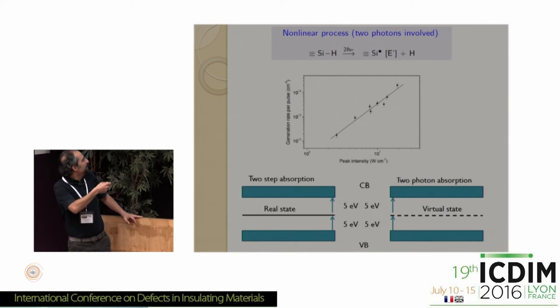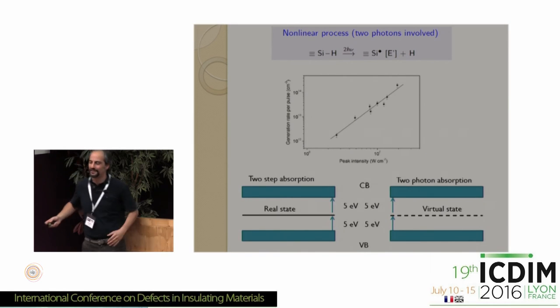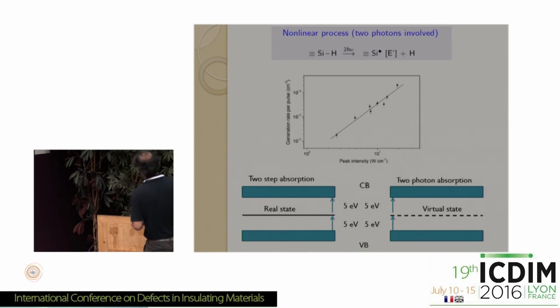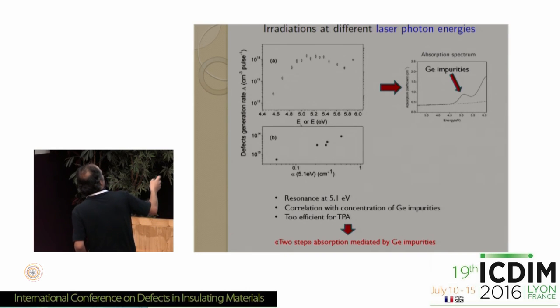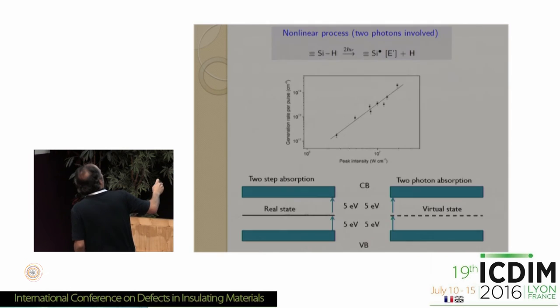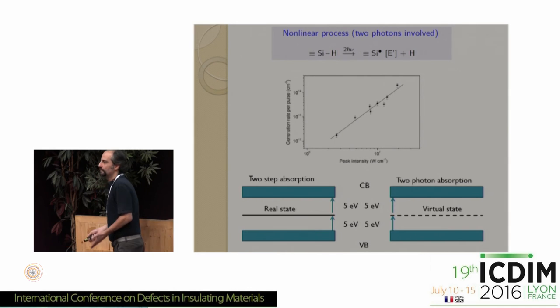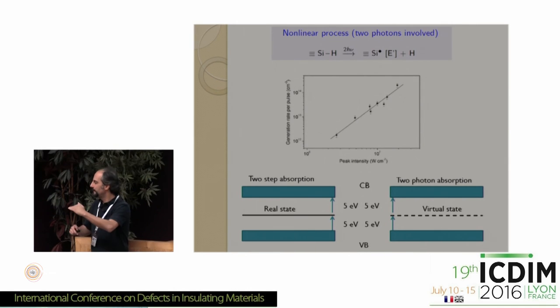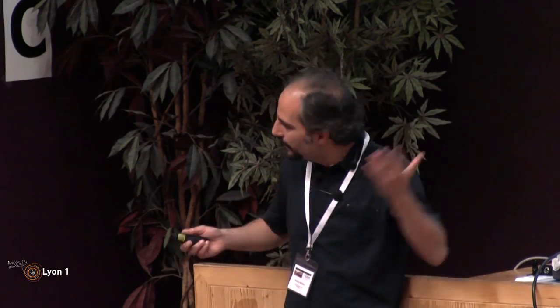Of course, I believe in the result that shows that an intermediate state is involved. I don't know why you don't. We can discuss it later. But simply, the generation rate of the defects is linearly correlated with the presence of this defect, while it's quadratically correlated with the intensity. So in my opinion, this proves clearly that you have a two-photon absorption mediated by a mid-gap state. Of course, this is an interpretation. Anyway, as for the first part of your comment, yes, I agree.